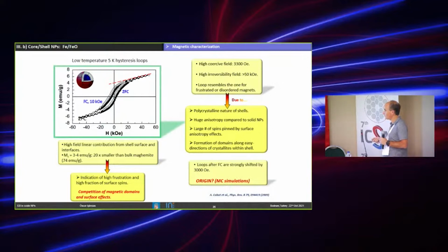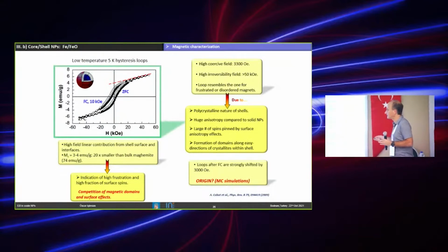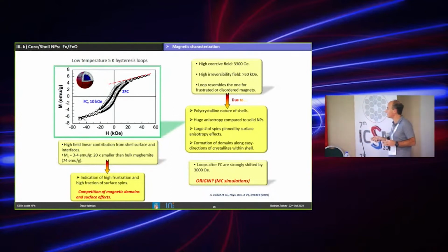And you notice here the very low magnetization, 2 emu/g when you project, or 4 emu/g when you project from high fields, right? Which means that, and why is this so? I mean, having a void particle doesn't mean that you lose all the magnetization of maghemite, which is more than 80 emu/g. Why is this happening?